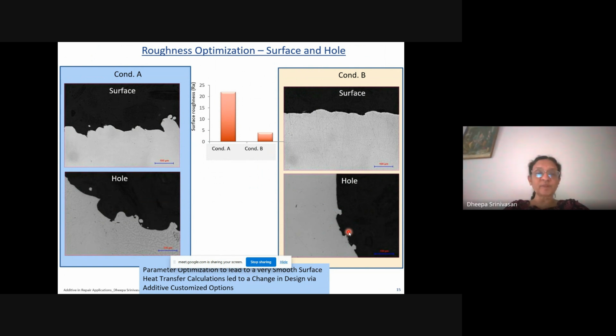Whereas in the laser powder bed fusion, whose example I'm showing you right now, you can do a little bit of process optimization using the laser parameters itself, the energy density variability, so that you are able to minimize the surface roughness, not only on the surface, as shown in condition A versus condition B, but also inside any geometrical features, such as a hole. So you can see that between condition A and condition B, the surface roughness has been reduced from nearly 20 to less than 5 micrometers Ra.